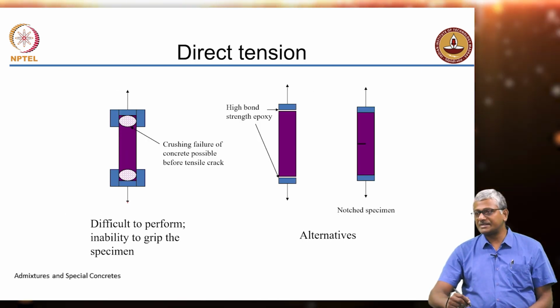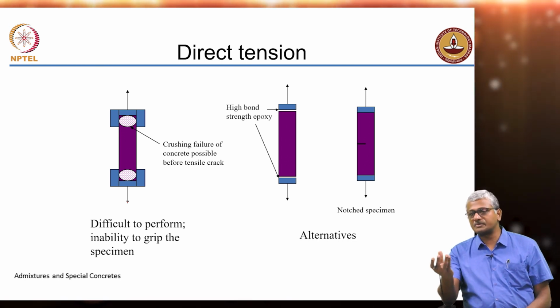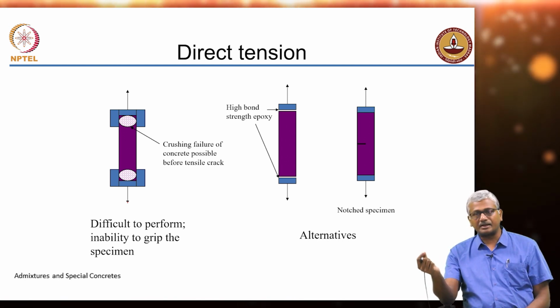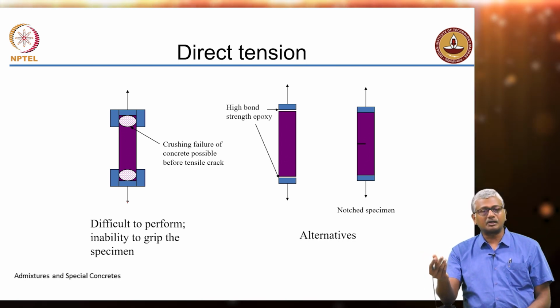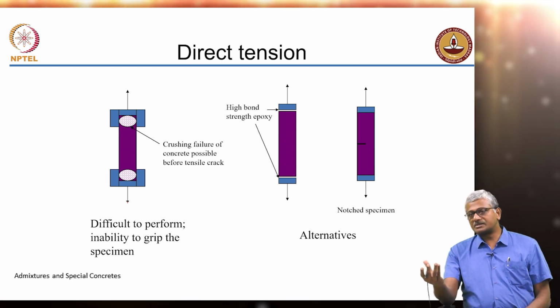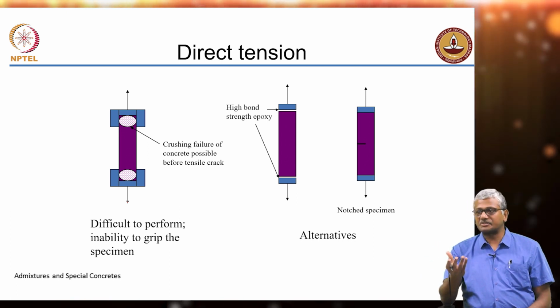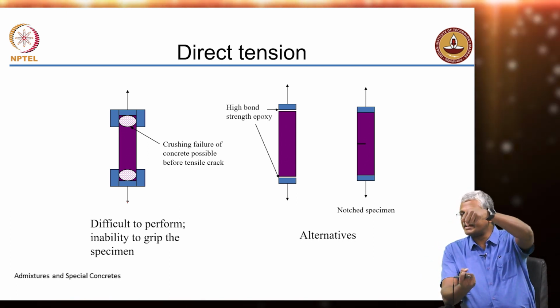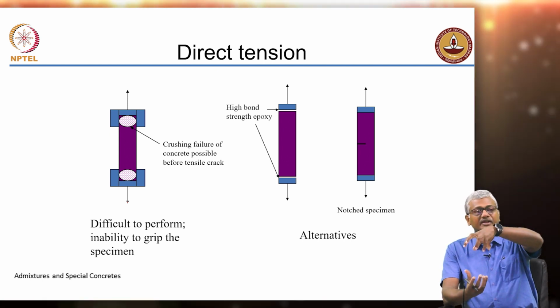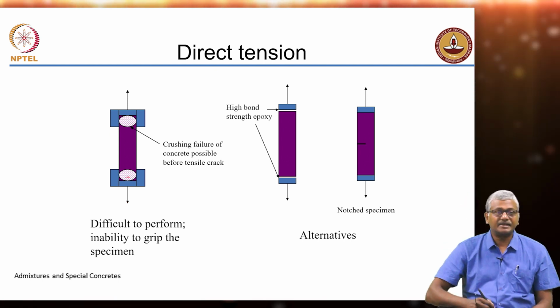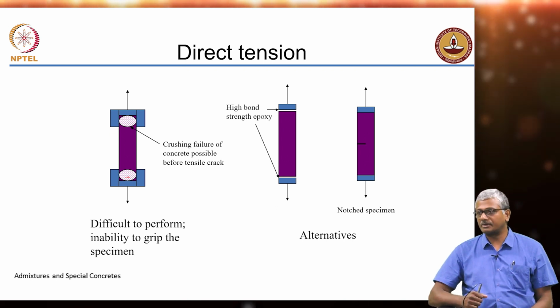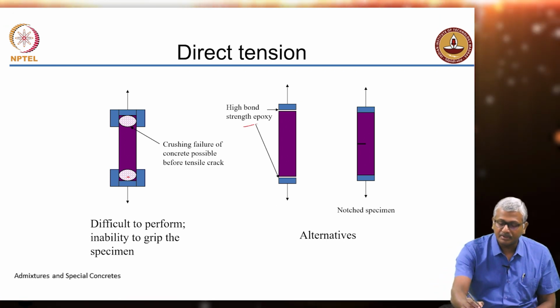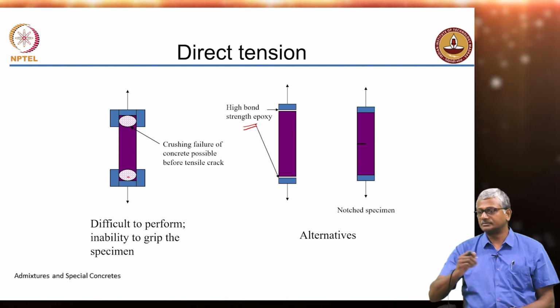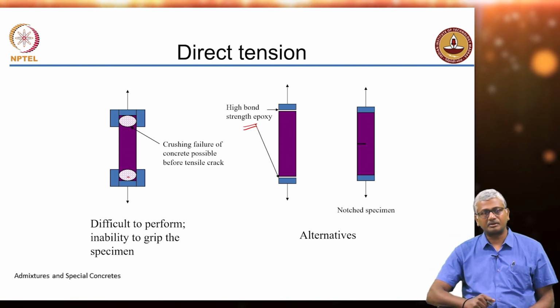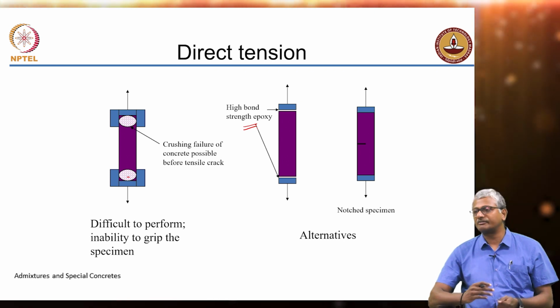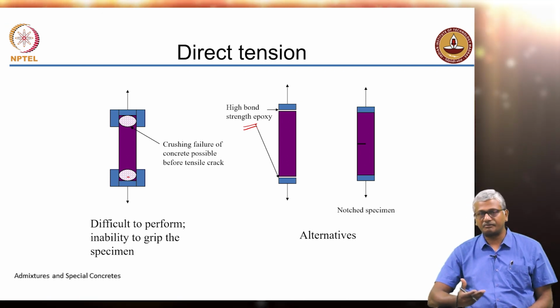Direct tension is not that easy to perform because concrete specimens have to be at least 3 times the size of the aggregate. If you are using 20 mm aggregate, you should use at least a 60 to 75 mm size specimen. Such a specimen, if you try to grip at the ends, may lead to a failure of the concrete by crushing at the ends rather than the tensile failure of the concrete itself. So, you may want to sometimes use a high bond strength epoxy at the ends to pull off the concrete, but if your epoxy is not strong, the failure will happen at the epoxy and you will not really have any failure in the concrete.